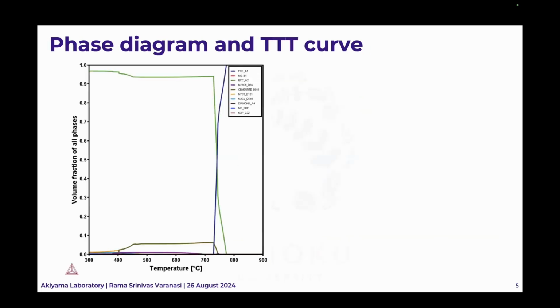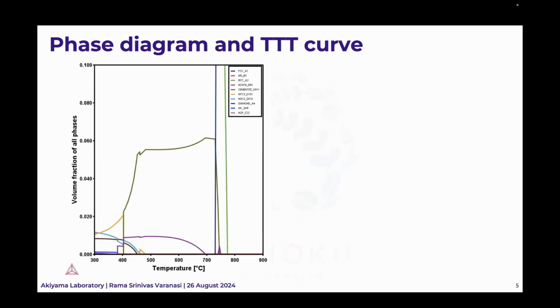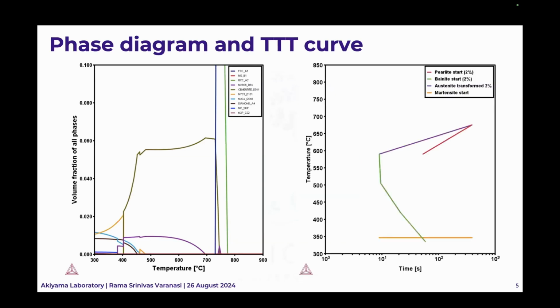When we look at the phase diagram, what we see is there are a lot of carbides which form at temperatures lower than like 750 or 800. So we confirmed with TTT curves that for whatever the temperature of Ausforming, we do not have any primary carbide precipitation. So if we want to understand the effect of Ausforming, we need two things. The first is the microstructure, and how Ausforming changed the microstructure. And the second is the effect of this microstructure on the hydrogen-assisted fatigue crack growth.